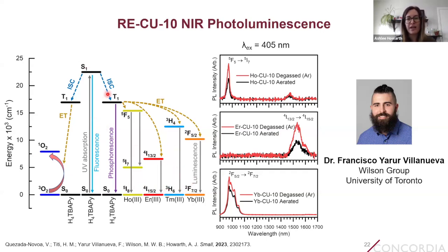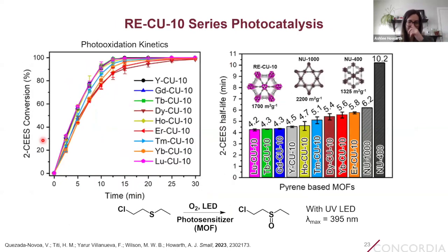And so because those energy transfer processes can compete with the generation of singlet oxygen, how does that affect the photocatalytic results that we see? Here, we have the photooxidation kinetics for all of these Cu10 analogs, so conversion versus time. What we see for all of these MOFs is that in all cases, the reaction still goes to 100% completion, and it's still selective to generate the sulfoxide, which is great.